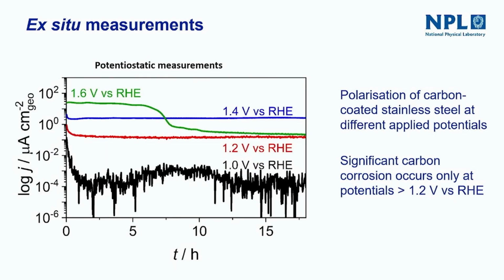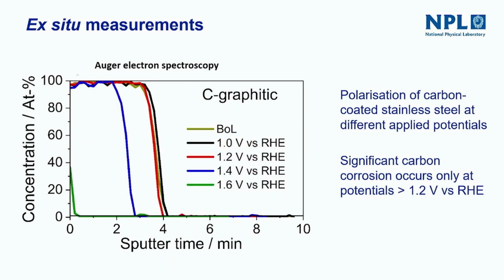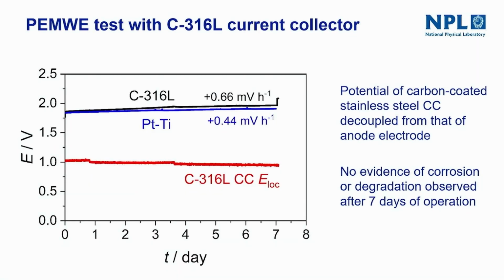I'm going to skip some of the detail here in the interest of time because I know we are running a little bit late, but most of these measurements just confirm that the bipolar plate is sitting at this decoupled potential. So we set up a cell for 7 days with a carbon-coated 316L current collector, and we showed that it sat at a completely different potential from the anode.